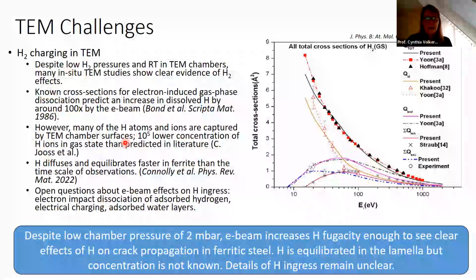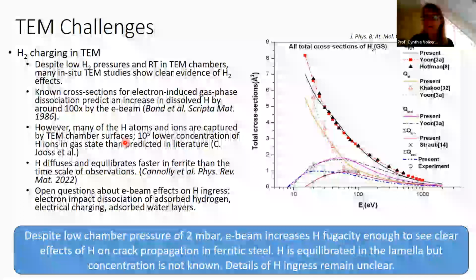One thing that we can say is that in ferrite, for the time scales we're dealing with and the length scales we're dealing with in these lamella, the hydrogen will have had time to diffuse and equilibrate on the time scale of our specimen. So whatever concentration of hydrogen we have in the specimen, it's been able to find its preferred sites within the material. And so it's free to move and find it and equilibrate there. So these are huge issues one has to think about. In our case, the result is we don't know what the concentration of hydrogen in our specimen is, but whatever it is, we believe it to be equilibrated. Okay, so that's the further challenge.